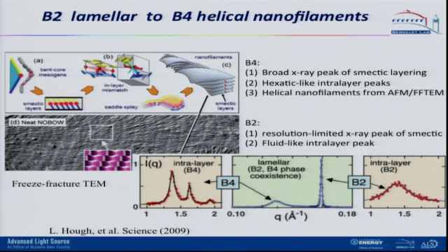But the point is that you have smectic layers, and then they stack up. For example, you have 5 to 8 smectic layers, and then they twist into a nanofilament like this. The filament diameter is about 20-30 nanometers, and the pitch, based on TEM results, is about 100 nanometers.